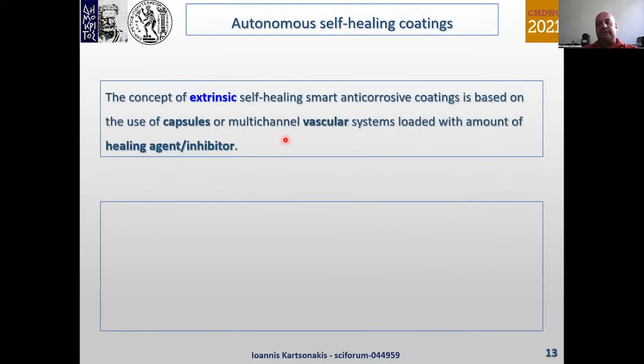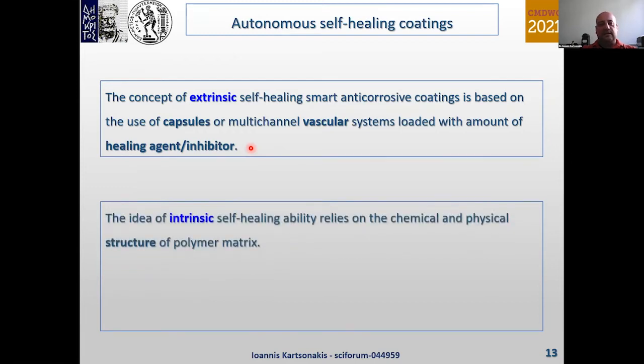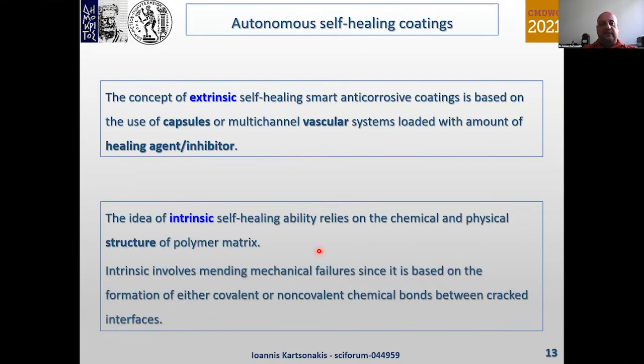The concept of extrinsic self-healing smart anti-corrosive coatings is based on the use of capsules or multi-channel vascular systems loaded with an amount of healing agent or inhibitors and catalyst if it is needed. And the idea of intrinsic self-healing ability relies on the chemical and physical structure of the polymer matrix. Intrinsic self-healing ability involves mending or repairing mechanical failures, since it is based on the formation of either covalent or non-covalent chemical bonds between the cracked interfaces.